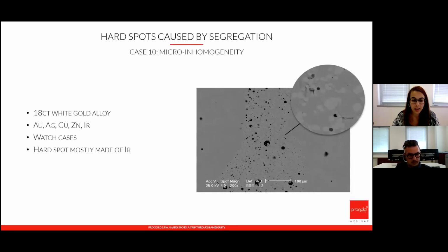In this case, we had a very specific section. Let's imagine that you have the whole bath, and then you start cutting small cubes of the bath, if it makes any sense. In some of the small cubes, you were not mixing enough. So in that specific point, the iridium that was inside was not solubilized, because maybe in another cube, in another part, there was not enough iridium because it was not mixed well together. So in that point, the hard spot came out due to solubility issues.